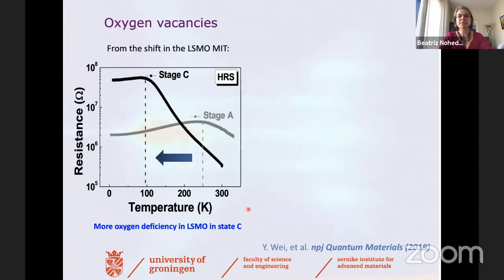In our case, things seem to be a bit different, and we notice that from stage A to stage C, the resistance versus temperature of our junctions is completely different. This particular shape is well known to be due to the LSMO electrode, the typical resistance versus temperature behavior of the LSMO. You can see that the bottom electrode is changing between stage A and C. And this particular shift of the resistance of the LSMO is indicative of the fact that in stage C, we are creating oxygen vacancies at the LSMO.